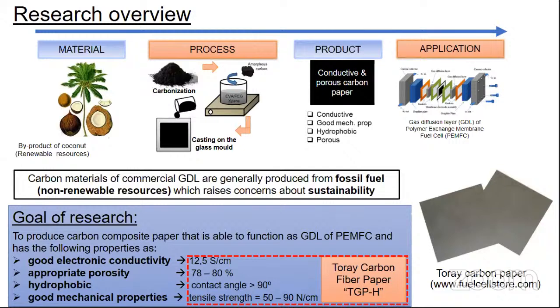To be applied as GDL of PEMFC, the paper should have the following properties: conductive, good mechanical properties, hydrophobic, and porous. Finally, for the application, we insert the paper in the stack of the fuel cell, replacing the commercial carbon paper as GDL, and test the performance in the PEMFC system. Carbon material used in commercial GDL is generally produced from fossil fuel. We know that fossil fuel is a non-renewable resource, which raises concern about sustainability. By using coconut waste, this sustainability issue can be resolved due to the renewable nature of coconut.